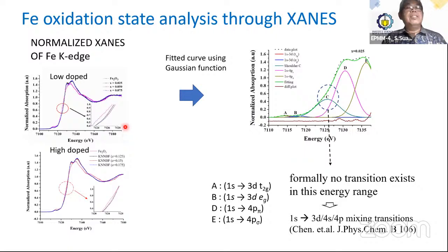The XANES analysis of the iron K-edge shows the pre-edge, the edge, and the maximum absorption of the crest. Further analysis by fitting using Gaussian functions reveals that the pre-edge splits into two peaks. Similarly, the crest also splits into two peaks. Here, we observe absorption peaks which are formally no transition exists in this energy range. It's suspected that this comes from the mixing transition of 1s to 3d, 4s, and 4p.